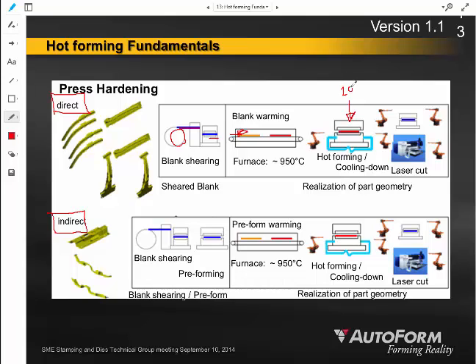Something in the ballpark of 200 to 80 degrees C, right? When you get this material down into the range of 200 degrees C to 80 degrees C, you've already cooled it sufficiently that it's going to have the appropriate microstructure. Then potentially you could use a robot to gingerly unload that blank, let it go down to the conveyor belt so that it can get racked, or bring it to another station for laser cutting, laser trimming. Right, this is what we would call direct press hardening or direct hot forming.